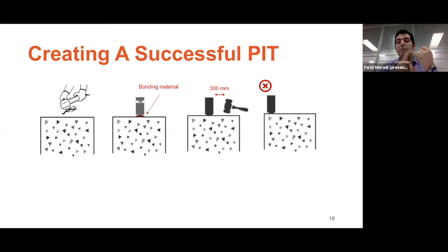You need to remove the debris, poor concrete, and contaminated materials to make sure there is a good contact between the sensors and the pile, in order to receive good quality signals. And for good contact, you can use some bonding materials. Bonding materials are not really expensive, like petroleum gel, the most famous being Vaseline, or putty, or wax, or any type of bonding material, just to make sure the sensor is in very good contact with your